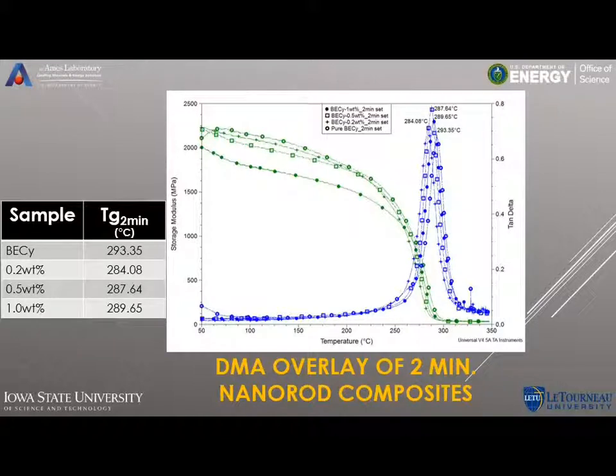For the actual data here, these are the 2-minute nanorod samples. So they had the smaller diameter nanorods in them. And you can see that we had, for the pure polymer of that set, a glass transition temperature of 293 degrees C. But for the 0.2%, that dropped down to 284 degrees C. So almost a 10-degree drop in temperature for the glass transition temperature.